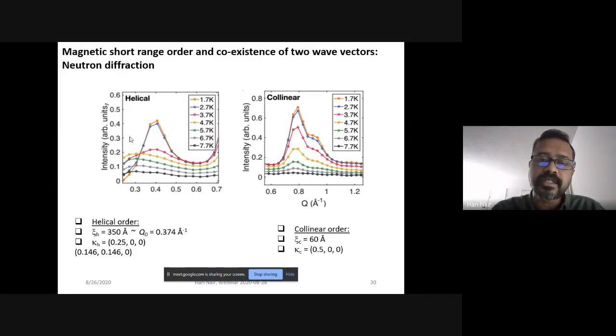So you can see that as the temperature goes close to 1.7 Kelvin, they peak up. And above 4 Kelvin, the helical peak is almost smoothed out. That's not so in the case of the collinear structure. In the case of the collinear structure, the peak formation begins already by 6 or 7 Kelvin. It means that one of these orders sets in at a higher temperature, and then the helical order sets in at a much lower temperature.